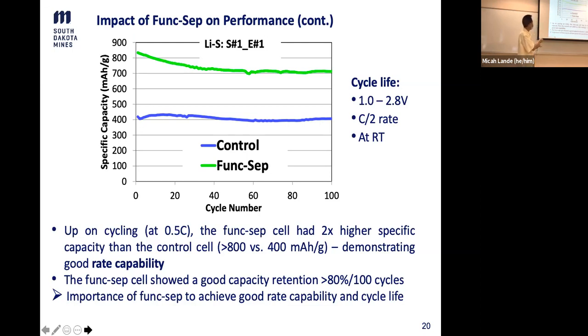So we are doing this in a controlled way, for many cycles, and we are looking at how our capacity is plotted against the cycle number. You can see that the advanced cell delivers almost twice the capacity throughout the cycles. The second thing we notice is that initially it's fading a little bit, but it becomes stabilized, and it lasts with more than 80% of the capacity after 100 cycles. So this is why this is important.